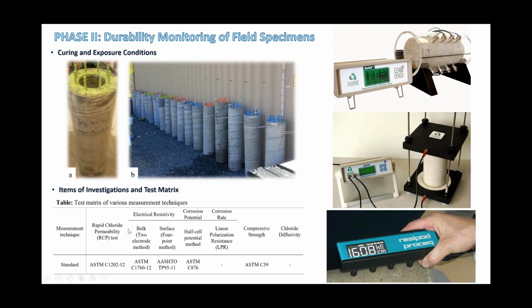I also use the linear polarization resistance technique to find out about the corrosion rate of my samples. I don't want to bombard you with too much information about my results, so I simply put a couple of graphs in here. I divided my columns along the height into 7 spots, and I measured them every 90 degrees apart. So you can see for mono columns, the electrical